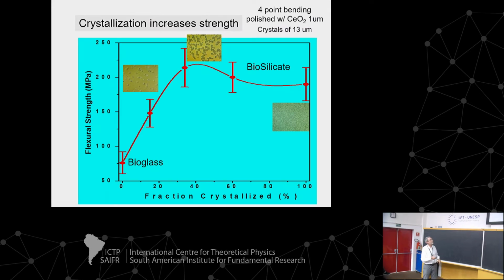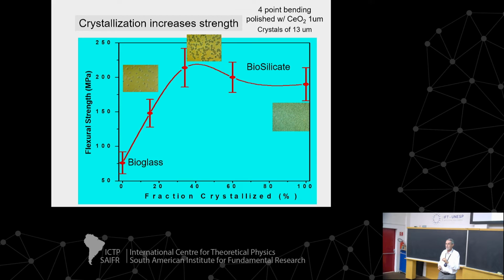And I'm going to give just two examples for you. Professor Hench invented bioglass in 1970. He came into our lab in 1980 because I was already working a lot on glass crystallization. He wanted to crystallize his bioglass to improve the strength without losing bioactivity. We did that after a few years, of course. We took his bioglass, we changed the chemical composition a little bit, and this is a partially crystallized bioglass, and you see the strength was 75 megapascal, went up to 220 or so. A 200% improvement in the strength of this bioactive material, just by controlling the crystallization process.